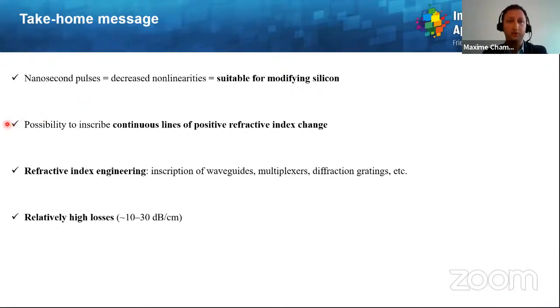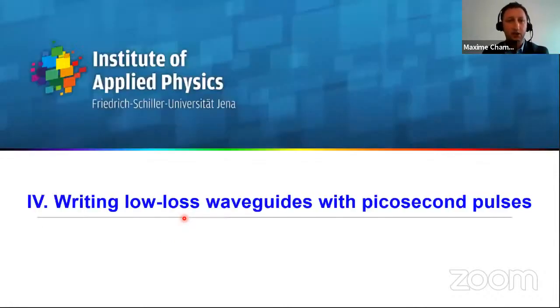It was possible to inscribe continuous lines of positive refractive index change. The refractive index engineering endeavors allowed us to demonstrate that it is possible to write long waveguides, multiplexers, and diffraction gratings. However, the losses were relatively high. And this is one point we addressed afterwards by endeavoring some picosecond laser irradiation for waveguide writing inside silicon. So here, the idea is to drastically decrease the damping losses of the waveguide, and access some new applications.